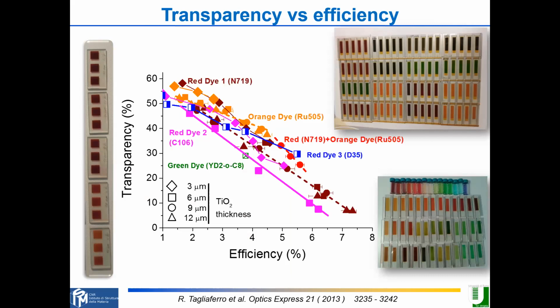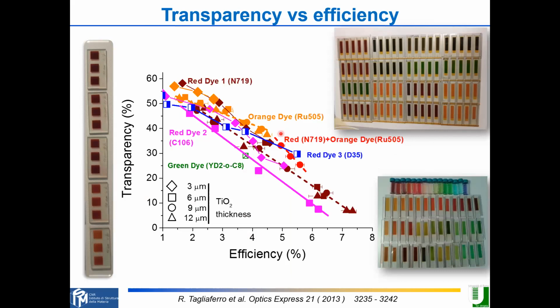And if you make a plot, let me show you the options. Sorry, this one. Okay, so you see a transparency and efficiency plot. By changing the thickness of the titania, the colors, the molecules, and so on, you can make this kind of plot that relates transparency and efficiency, which is quite good. I mean, you can get 5% with 40–50% of transparency for this kind of solar cell.